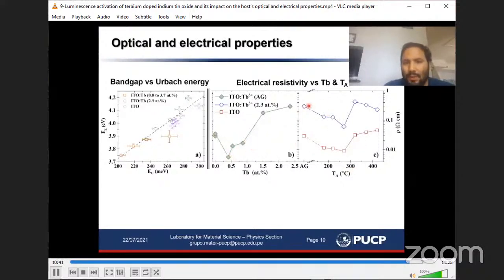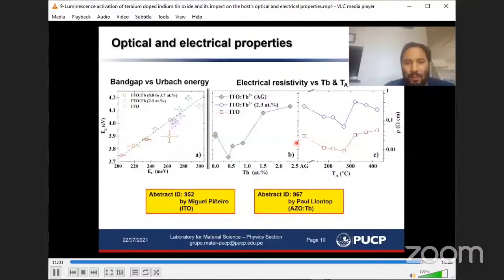Here on the right, I'm showing you the electrical resistivity of a sample with 2.3 atomic percent of terbium versus the annealing temperature. And on the red curve, I'm showing you the evolution of the electrical resistivity with annealing temperature of a sample without any terbium, grown under similar conditions. So again, if you're interested in checking the optical and electronic properties of ITO grown under these conditions, you can check this work. And if you're interested in learning about the energy transfer mechanisms in terbium-doped aluminum zinc oxide films, you can check this other work, which is also presented in this conference.